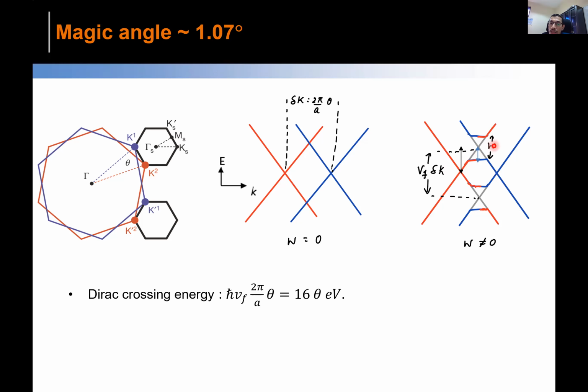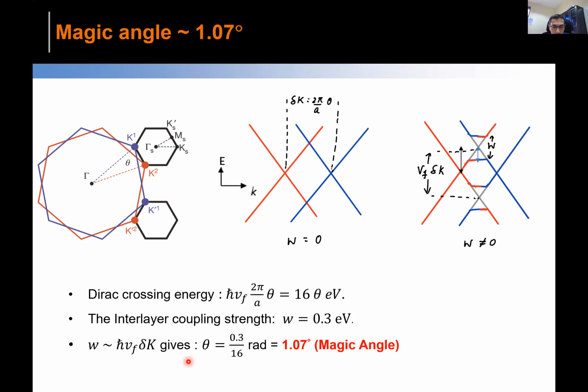Now we know that this w, the interlayer tunneling in graphene, is very well known, and in fact it is 0.3 eV, the coupling strength. So I have to push this band by 0.3 eV, and then this line will be completely flat. So basically I have to equate this number to 0.3 eV to find what theta will be. If I do that simple exercise, in fact, that gives me theta equal to 1.07 degrees.